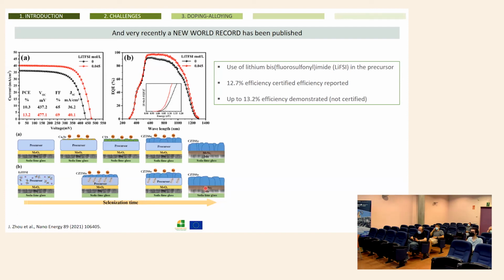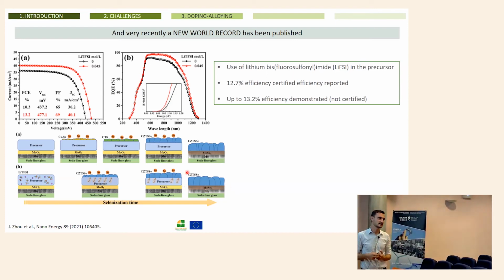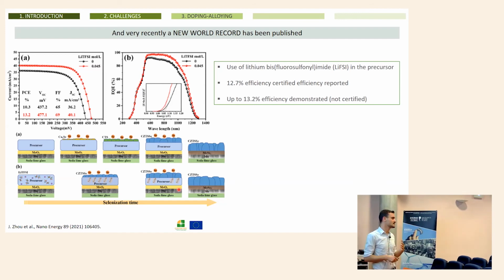And this is a very nice selective hole transport layer, a selective contact for holes, and it's formed naturally in the compound. It's the same in CZTS. So in that sense, we were very lucky with this. Basically, for CZTS, there is no other back contact than molybdenum that works well. So we need to use molybdenum first because it fulfills all the properties to be a very good back contact, but also because molybdenum selenide or molybdenum sulfide is naturally formed, and you can have here a hole selective contact.